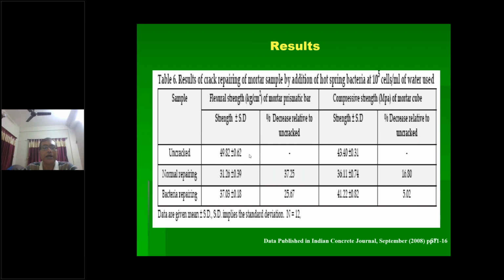What we get in these cases, there is the uncracked condition. That is, if we do not provide any cracks, then what is the flexural strength? It is 4.9 MPa, and compressive strength is 43 MPa. And if we do the normal repairing, after forming this, what we get is 3.1 MPa as flexural strength, and 36 MPa as the compressive strength. So somehow we are getting less, although we have repaired it, as the cracks have been poured and repaired by normal mortar.